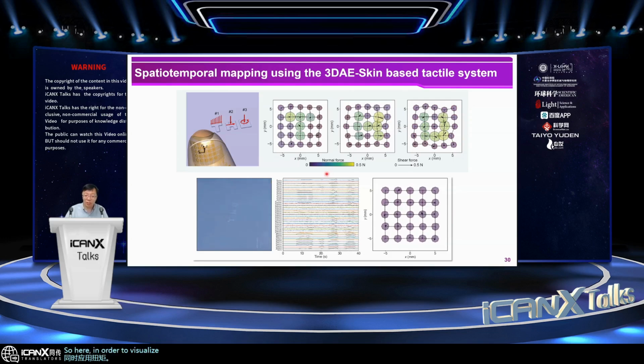So here, in order to visualize the tactile information, we have proposed this type of spatial temporal map. So here you can notice 25 octagons in this map, which correspond to the 25 units in our 3D skin device. And for each octagon, the size or the color denotes the magnitude of the normal force. And the black arrow represents the shear force, including the magnitude and the orientation. The longer the arrow, the larger the shear force. And also, the spacing between adjacent octagons denotes the strain magnitude along the horizontal and vertical directions. So here, based on this spatial temporal map, you can clearly see the tactile information very intuitively.